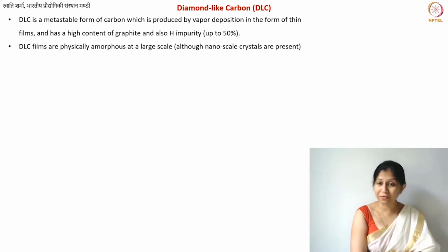That is also the case with diamond-like carbon films, because you have both diamond and graphite type crystallites at the nanoscale. So you only have short range order. You pretty much never have long range order in the case of diamond-like carbon, but at the nanoscale you do have crystallites present. However, one more thing which is different compared to non-graphitizing carbons: here the electrical and thermal properties of diamond-like carbon films vary a lot, because you have an insulator and conductor mixed together, in different fractions. And it is a polycrystalline type of film, so you cannot really say these are the exact properties of this material. That is why you can never say that this is electrically conductive or not, and depending upon the fraction of sp2 type carbon, it will change.